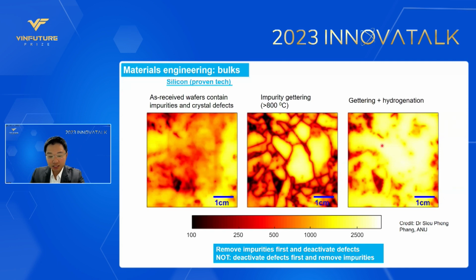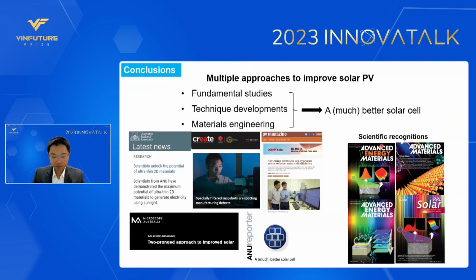So what we found out is that we need to remove the impurity first, and then deactivate the defect, not the other way around. Because if we deactivate the defect first by hydrogenation, the hydrogen atoms will leave the sample during the impurity gettering. So that's one of the findings that we give back to the cell fabrication team.